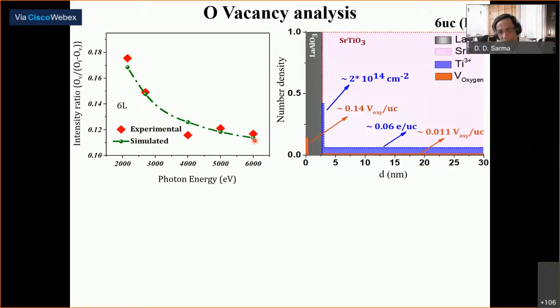And the model that works to describe the oxygen vacancy claims that there's a more or less constant oxygen vacancy all through strontium titanate. Not very surprising. Strontium titanate is known to have oxygen vacancy rather easily. And right at the surface of the lanthanum aluminate, there's some oxygen vacancy. And quantitatively, this oxygen vacancy here is about 0.14 oxygen vacancy per unit cell.